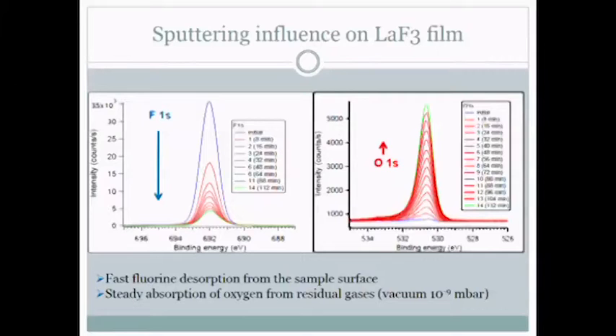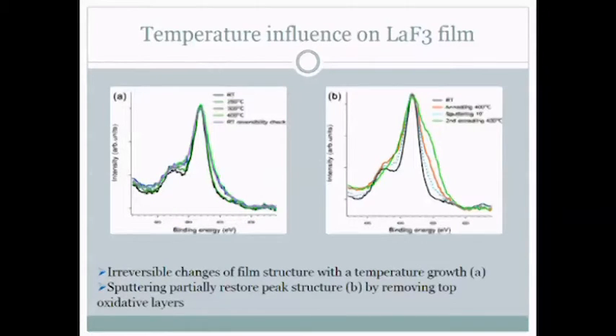So we've got clean lanthanum fluoride on one spot under the beam. And if we move it and insert some other gas, for example, or liquid, iodide or something else, we could change the material at this particular point. So this could be interesting, and it could be used. Next, which is also quite important, temperature more or less gives us the same results. The fluorine lattice is not as stable as lanthanum, and with increase of temperature, you could see the shift of the peak or broadening, which also points to fluorine loss and its substitution with oxygen on the surface.